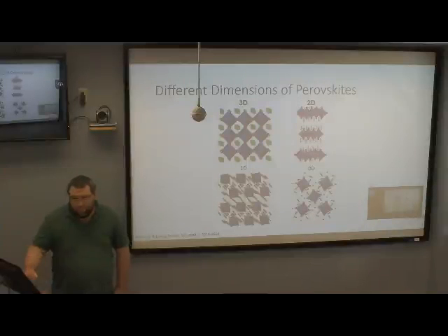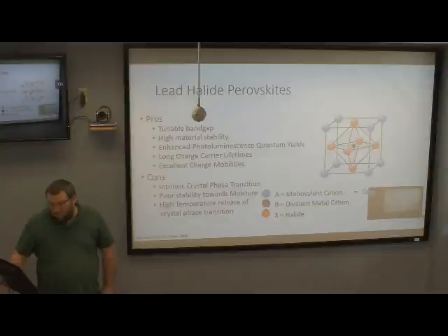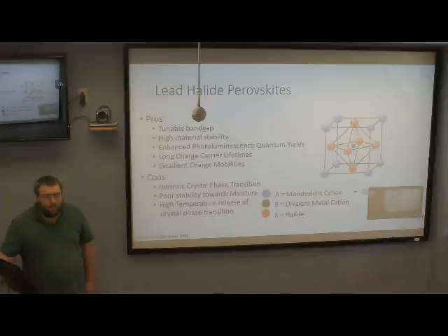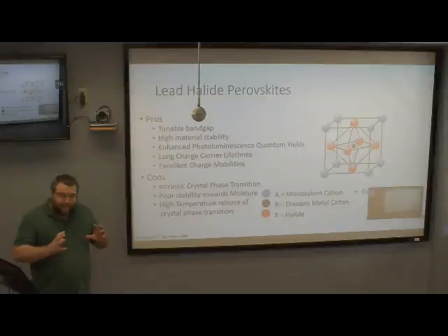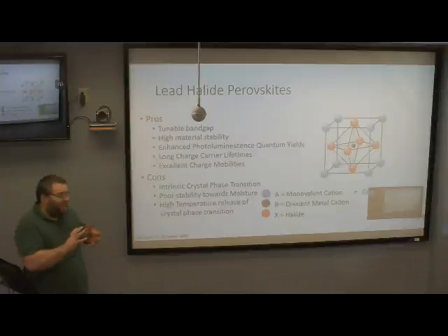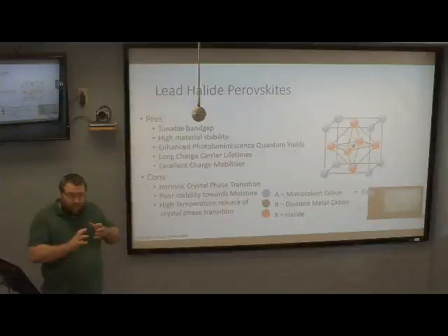I guess just one quick comment. Can you give a good reason, or an intuitive reason, why it would have poor moisture stability? In bulk, it's an ionic structure, and so it dissolves readily in water because of that.